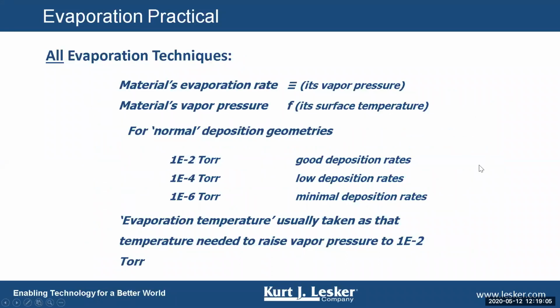When we talk about evaporation, basically we're talking evaporation rate, and it's somewhat equivalent to the vapor pressure of the material. And the material's vapor pressure is dictated by its surface temperature. The hotter a material gets, the more it approaches its evaporation point, and the colder a material is, the less likely it is to evaporate. For normal deposition geometries, we consider a material vapor pressure of 1 × 10⁻² torr high enough to give good deposition rate. And I'll show you a chart in a second that will cover that. But I'll use evaporation temperature, and by that I usually mean the temperature required to raise a material's vapor pressure to 1 × 10⁻² torr.